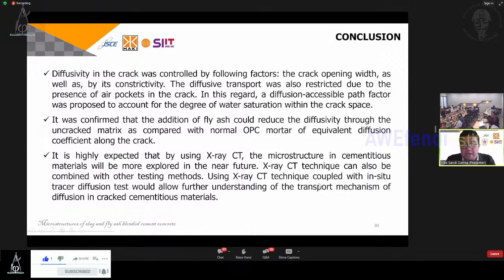X-ray CT again can be combined with another testing. You can combine with diffusivity, permeability. You may check the change in the crack due to high temperature exposure and recuring, and then you may apply any condition. And finally, using the X-ray CT coupled with in situ tracer diffusion test would allow further understanding of the transport mechanism of the diffusion in the cracked cementitious material. And then for the bonus, recently we also conduct another test, not only using the fly ash, but now we use SAP, super absorbent polymer.